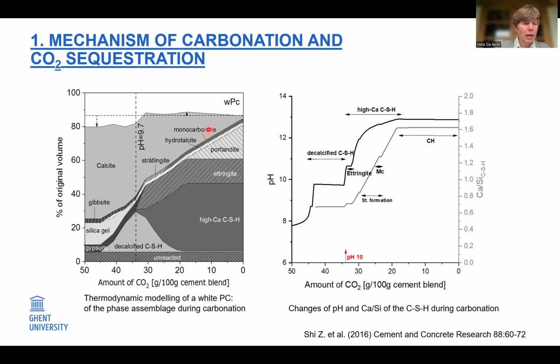And then we have monocarbonate that decomposes to stratlingite, and the decalcification of the CSH continues down to a calcium silicon ratio of about 0.75 and a pH of around 11. And then stratlingite and ettringite decompose, and the CSH decalcifies to the calcium silicon ratio of around 0.67, while the pH is further lowered to 10. And then finally, the CSH is decomposed completely into calcite and silica gel, and the pH drops rapidly further to 8.5.